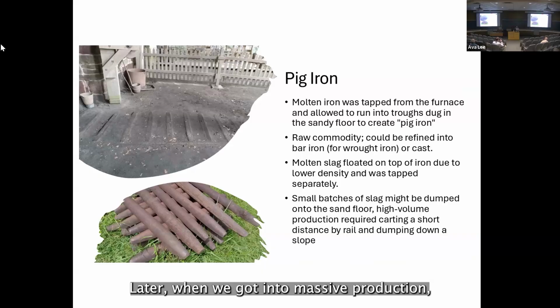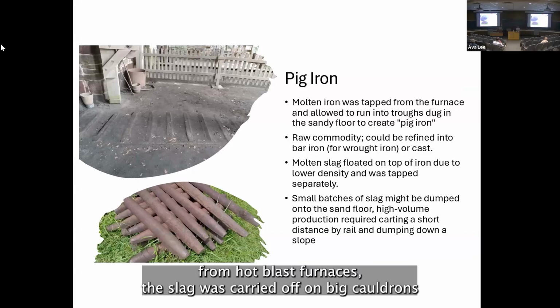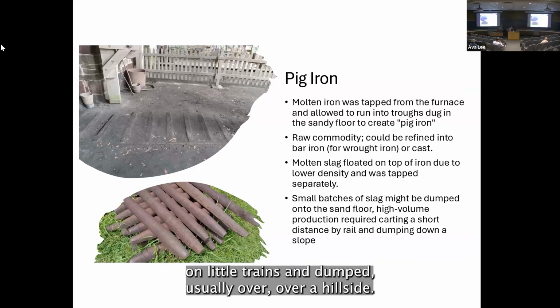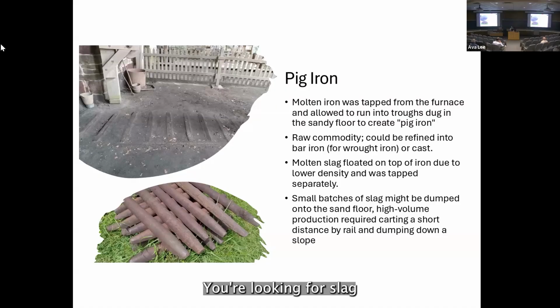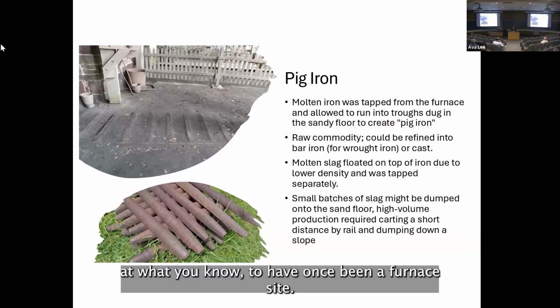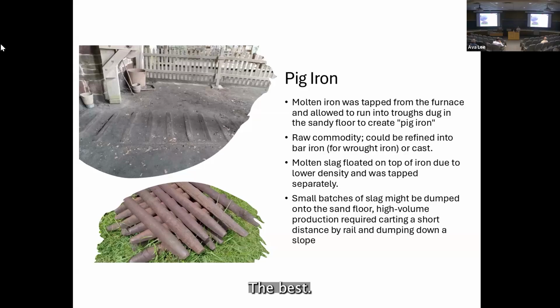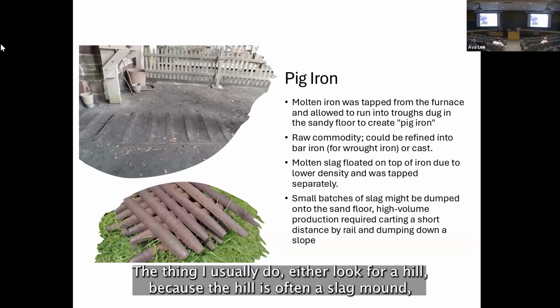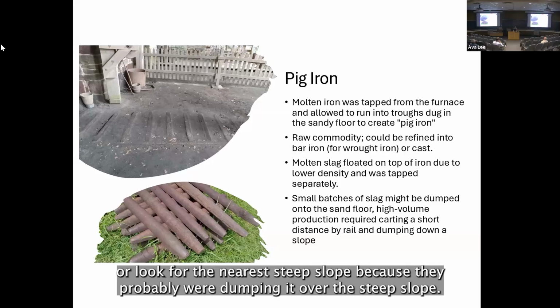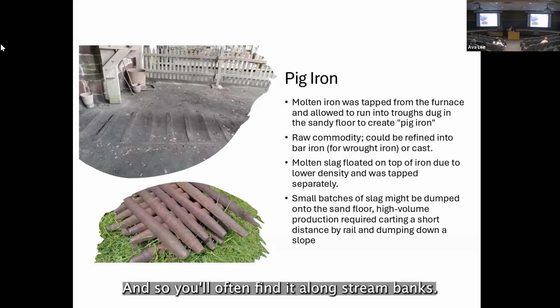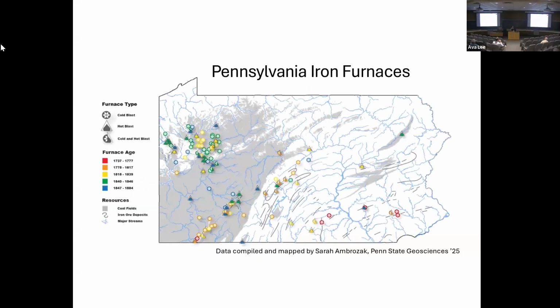Later, when we got into massive production from hot blast furnaces, the slag was carried off on big cauldrons on little trains and dumped usually over a hillside. If you're looking for slag at what you know to have once been a furnace site, the thing I usually do is look for a hill, because the hill is often a slag mound, or look for the nearest steep slope, because they probably were dumping it over the steep slope, and so you'll often find it along stream banks.